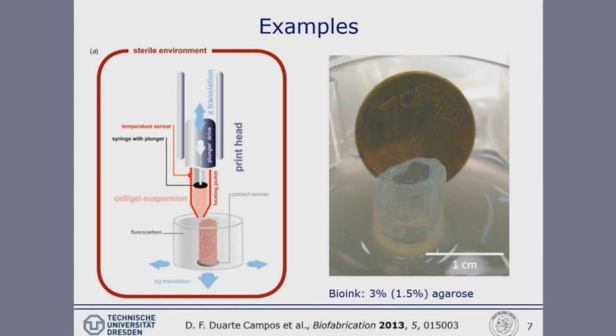And this was done with a rather low-concentrated agarose biopolymer hydrogel as bioink, which definitely would collapse if you would print in air, not having this stabilizing but inert liquid. Fortunately, these ultra-hydrophobic solvents are good solvents for oxygen and therefore support survival of the cells. But of course, finally, after some cross-linking process, you have to put your construct in the normal incubator in aqueous cell culture media.